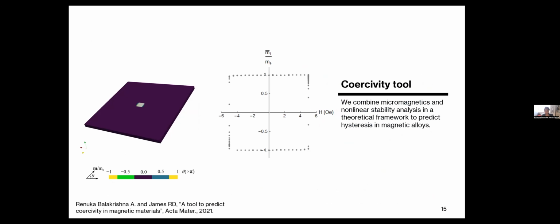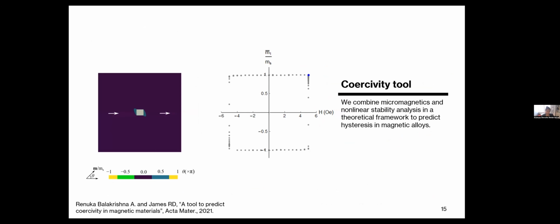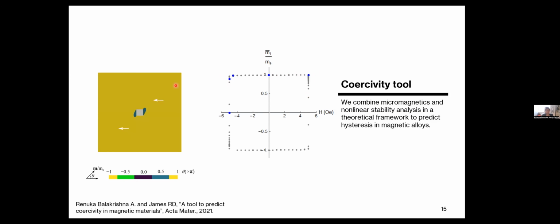Okay, so using this method, I can show you an example of a simulation of how it looks like. So this is the three-dimensional one. We're looking at a cross-section of it. I'm showing this to you in 2D, but the computation was 3D. So you uniformly magnetize it along one direction. So this is what you see, with more or less a saturated magnetization there. And now what you do is you start to decrease the applied field in this direction, which causes your needle domain to grow. And as you lower the field and you switch to the opposite direction at a specific critical value, this needle domain grows abruptly and results in complete magnetization reversal. And that value of your external field is what we extract as the coercive force or the coercivity.